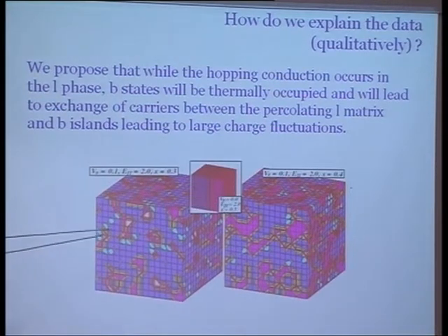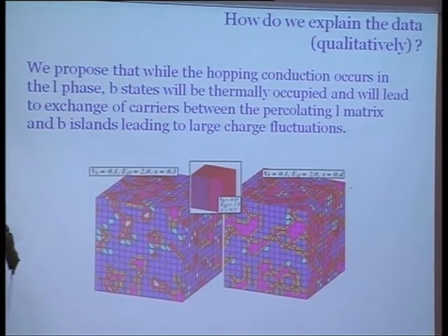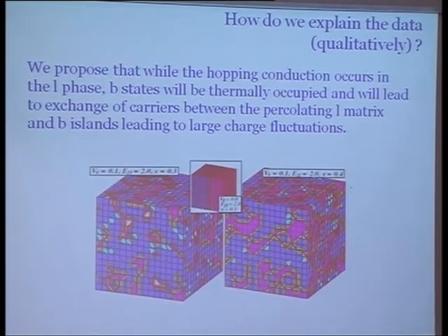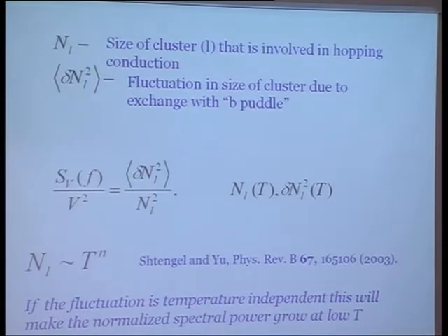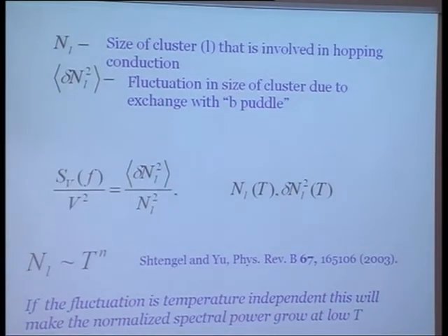In a static picture, they may look identical, but we can have exchange of carriers between them. If you have exchange of carriers between them, then we are going to get large charge fluctuations coming in. Now we can look into it. When I have the normalized power spectrum, essentially I'm talking of the ratio of the fluctuation of the size and the size itself. This is the size of the cluster that is involved in hopping conduction, and this is the fluctuation in the size of the cluster due to the exchange of the carriers in the B puddle. But the important point is that both of these are temperature dependent, so ultimately the temperature dependence that you are going to see will be determined by the temperature dependence of these two parameters.